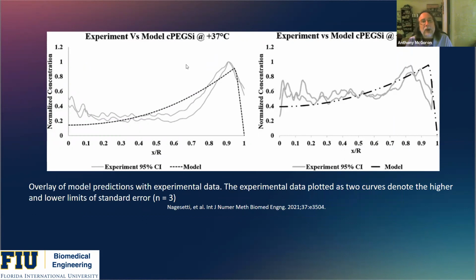And so what we show is data from the fluorescent nanoparticles between the surface of the spheroid towards the center of the spheroid for 37 degrees and 43 degrees. We see a greater leveling out of the distribution of the nanoparticles into the center of the spheroid at 43 degrees. And we see a very good fit between our model and our actual data.